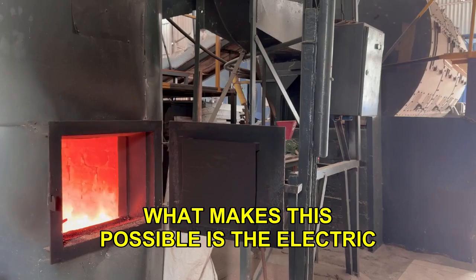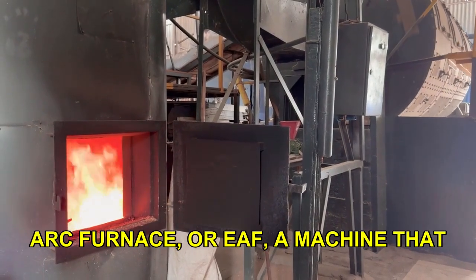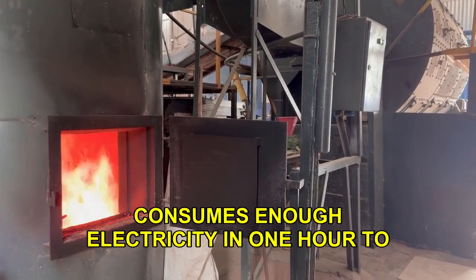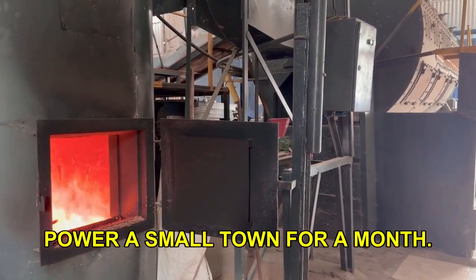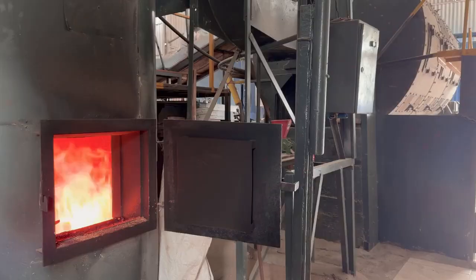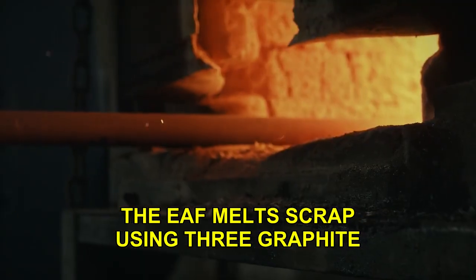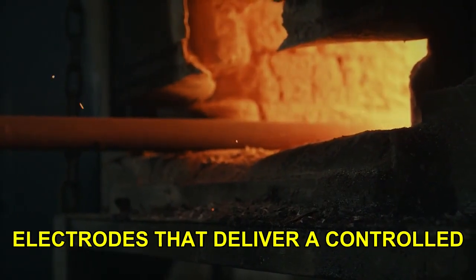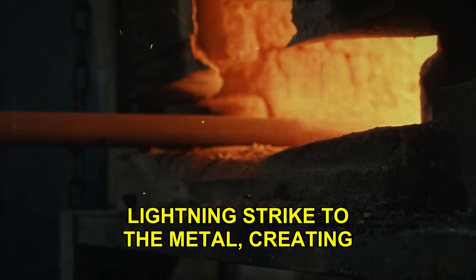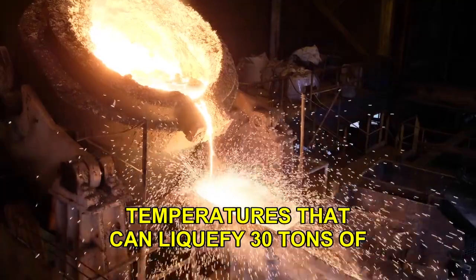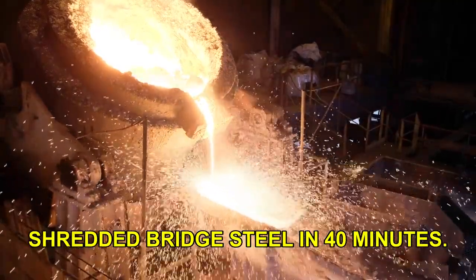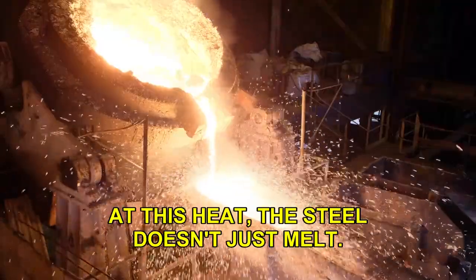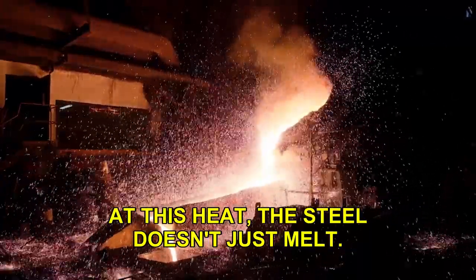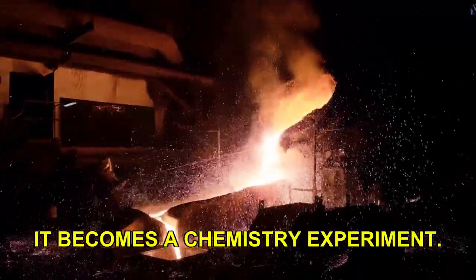What makes this possible is the electric arc furnace, or EAF, a machine that consumes enough electricity in 1 hour to power a small town for a month. The EAF melts scrap using 3 graphite electrodes that deliver a controlled lightning strike to the metal, creating temperatures that can liquefy 30 tons of shredded bridge steel in 40 minutes. At this heat, the steel doesn't just melt, it becomes a chemistry experiment.